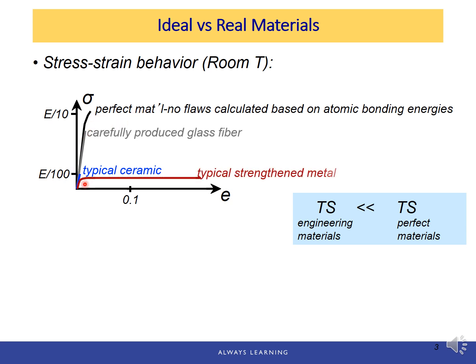And next, we have typical strengthened metal. It's quite ductile, but again, the measured tensile strength is much lower than the perfect material. And lastly, we have typical polymers. It's even lower. So therefore, we say the tensile strength of the measured engineering materials is much lower than the tensile strength of perfect or ideal materials based on the calculation of atomic bonding energies.